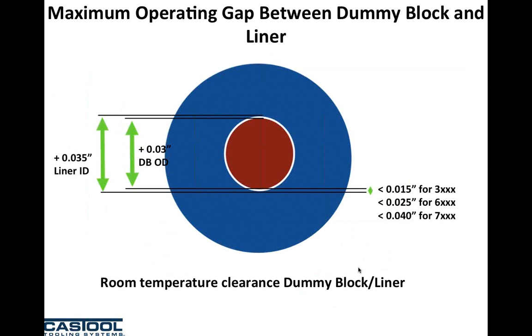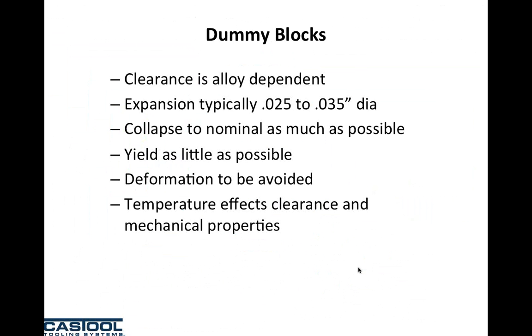And again, this maximum gap for 3000 series alloys is about 15 thou. 6000 series alloys is about 25 thou, and for 7000 series is about 40 thou. So as we get involved with alloys with lower flow stresses, the gap or critical gap between the dummy block and container at operating parameters becomes smaller. Dummy block clearance is alloy dependent. Clearance becomes more critical with soft alloys than it is with hard alloys.